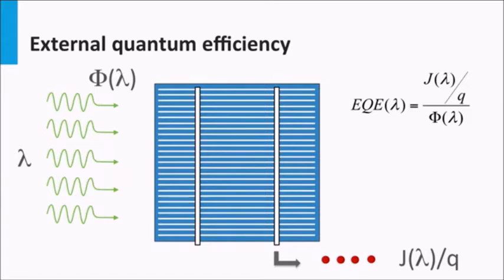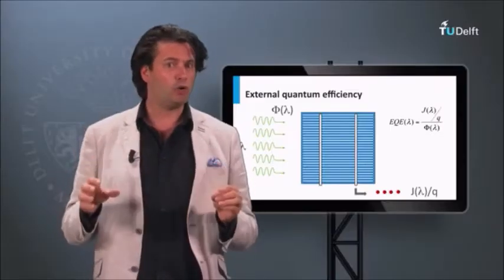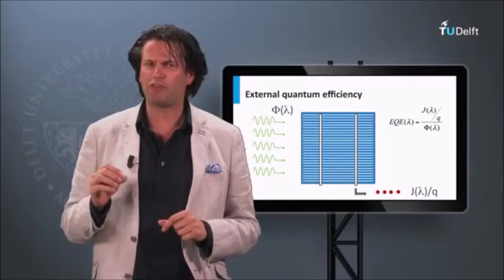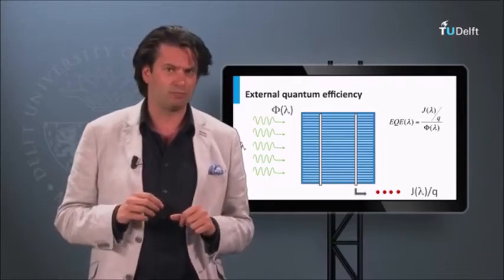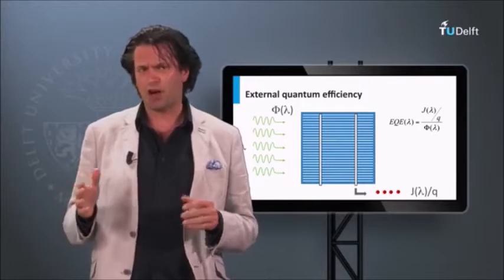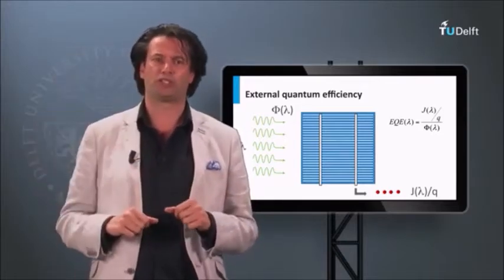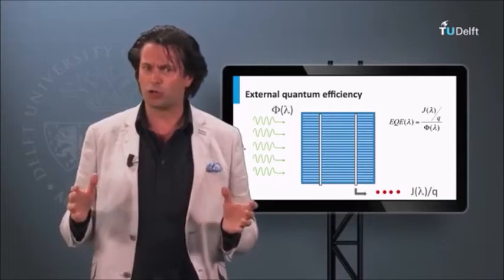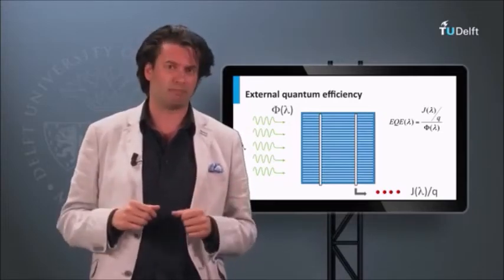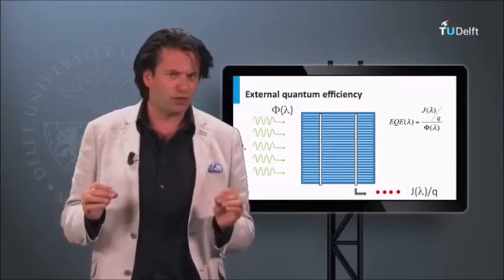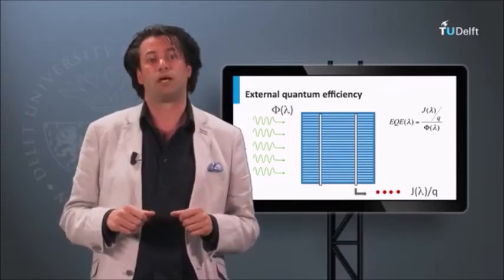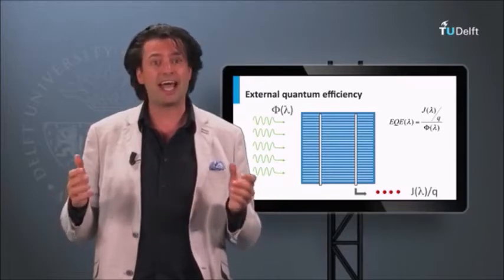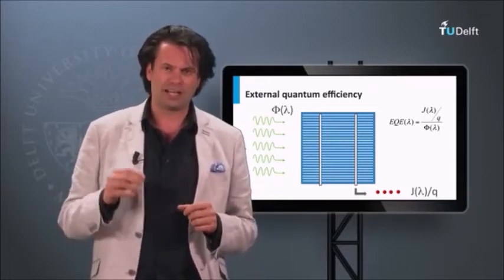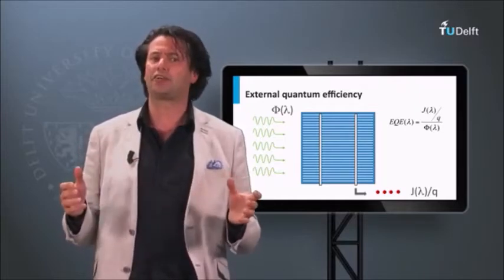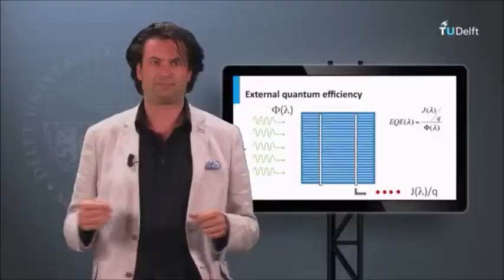Not every photon incident on a solar cell will result in electrons collected at the contacts. Lower EQE can be attributed to several optical and electrical loss mechanisms for charge carriers. For example, photons can be reflected back from the solar cell. Photons are not absorbed as they have an energy smaller than the band gap. The absorber layer is too thin and does not absorb all photons. Parasitic absorption losses in the inactive PV layers of the cell. And recombination of the light-excited charge carriers before they are collected at the contacts.